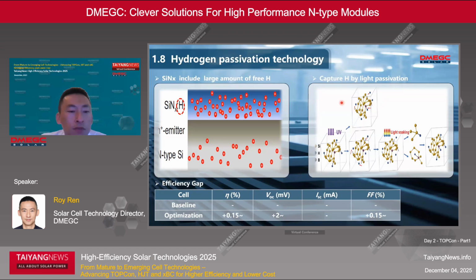Next is the hydrogen passivation technology. We know that the silicon nitride film layers contain a large amount of hydrogen. Some hydrogen exists in a free state. We found that light induction of different intensity can excite this free hydrogen to further passivate the silicon interface. Through light induced passivation, we achieve a 0.15% efficiency improvement from VOC and the fill factor.